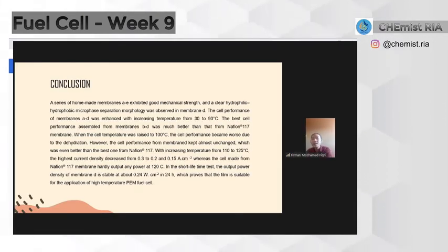Next, conclusion. A series of membranes A to E exhibited good mechanical strength, and a clear hydrophobic microphase separation morphology was observed in membrane D. The cell performance of membranes A to D was enhanced with increasing temperature from 30 to 90 degrees Celsius. The best cell performance assembled from membranes B to D was much better than that from Nafion 117 membrane. When the cell temperature was raised to 100 degrees Celsius, the cell performance became worse due to dehydration. However, the cell performance from the membrane kept almost unchanged, which was even better than the best one from Nafion 117.